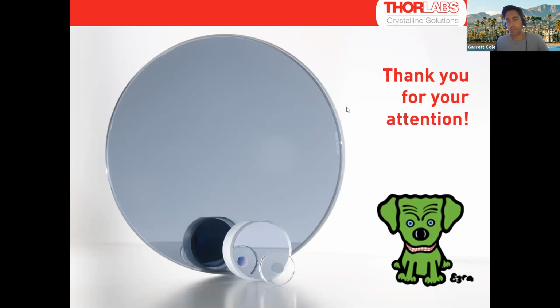It depends on the materials combination. So YAG and sapphire are almost perfectly matched. We could heat that up until we degrade the gallium arsenide. But for things like glass or other materials, we have to be careful. Same with the cryogenic optics. We have to really optimize the bond strength. So when we cool those at cryogenic temperatures, we don't spontaneously have the coating fall off, which most customers aren't happy about, their coatings falling off of their optic.